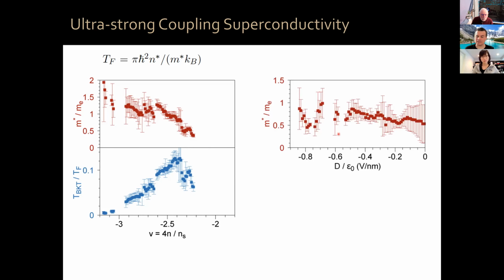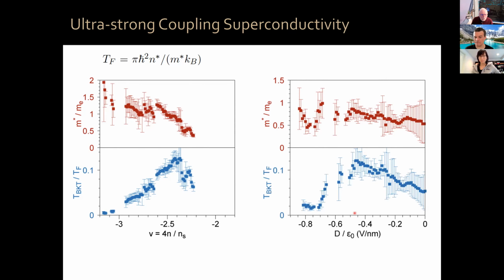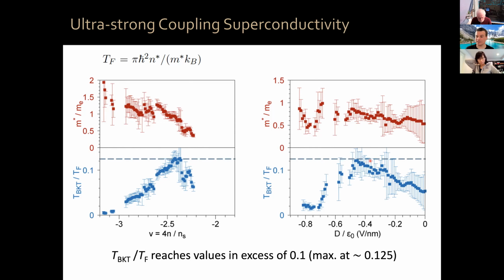We can do the exact same thing as a function of displacement field at optimal density, and you have the TBKT over TF. The dashed line indicates 0.125. As you can see, TBKT over TF reaches values in excess of 0.1, with the maximum at 0.125 for this system. Now, I don't want to make too much of a deal out of this exact 0.125, because that upper bound is for a system of cold atoms, where the mass of the boson is clearly twice the mass of the fermionic atoms that condense. For electrons, this doesn't necessarily need to be the case, but still, this system reaches values of TBKT over TF which are the highest for any superconductor.